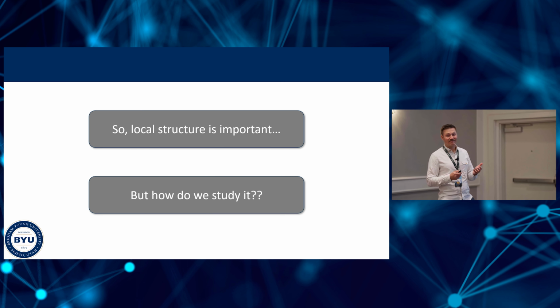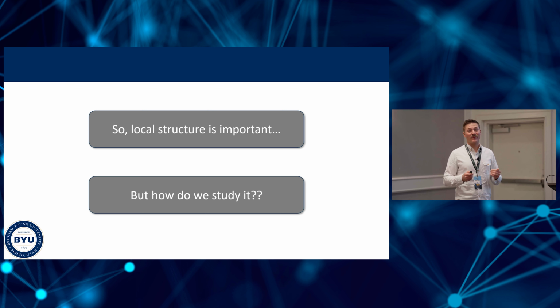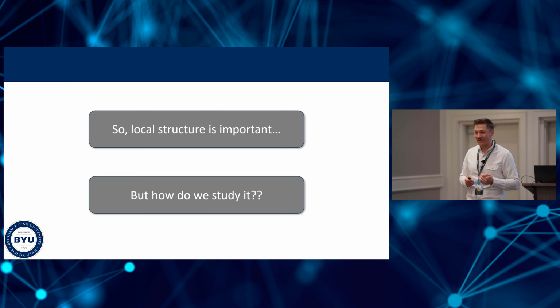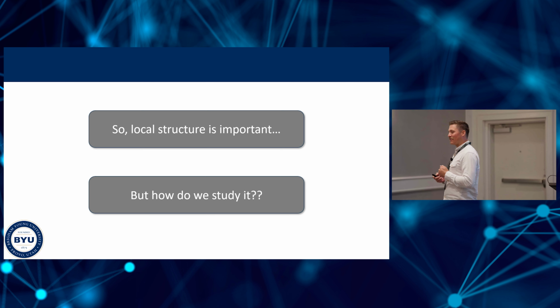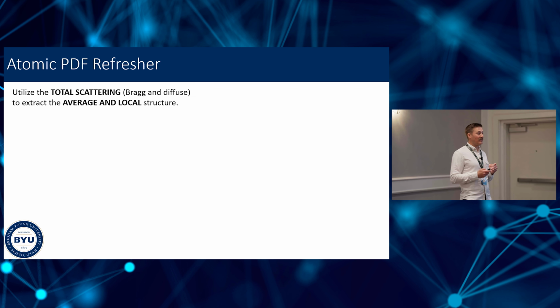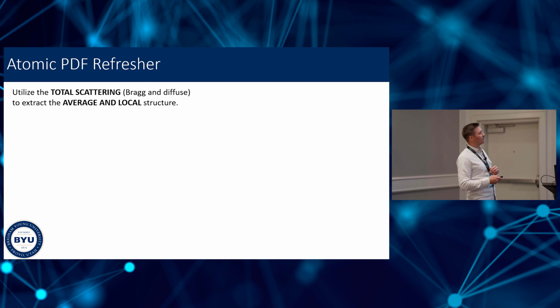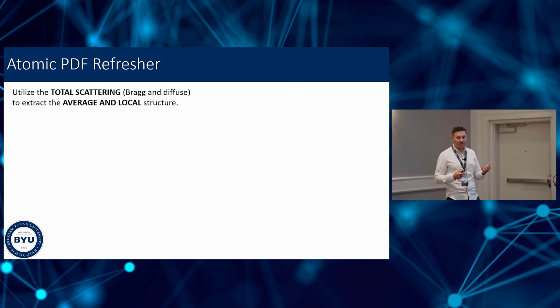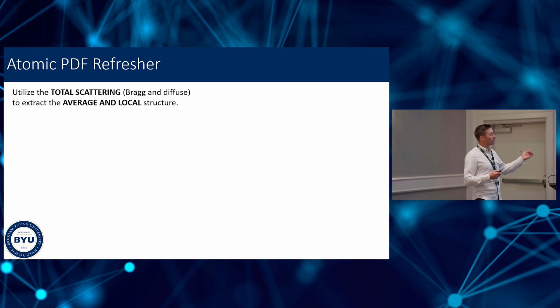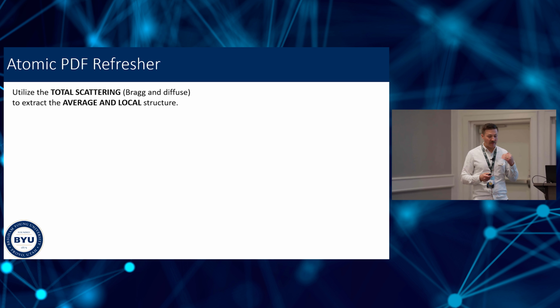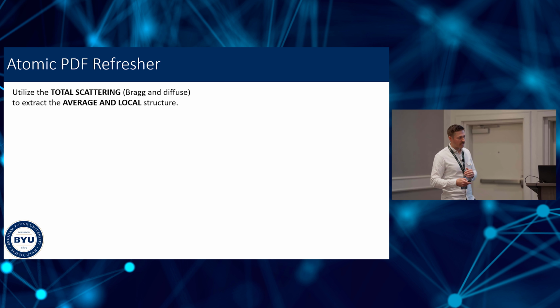Okay, so hopefully I've convinced you that local structure is important. How do we study it? We can't just look at the Bragg peaks, because that just gives us the average structure. So we have to look at the diffuse scattering. One popular way to do this is the atomic pair distribution function method, PDF. So here's a quick refresher. It's a total scattering method, and we're utilizing the Bragg and diffuse scattering. It gives us information about the average and local structure.